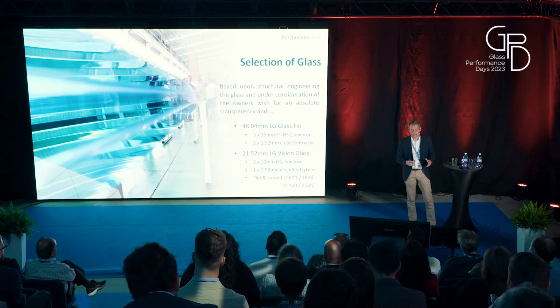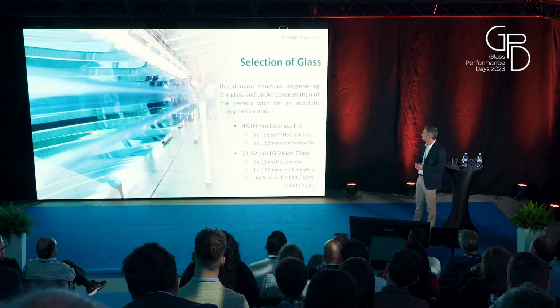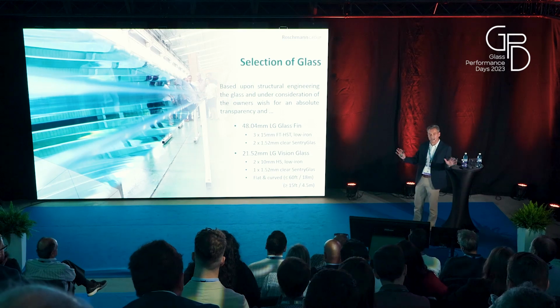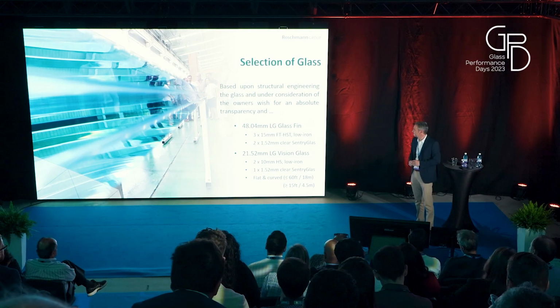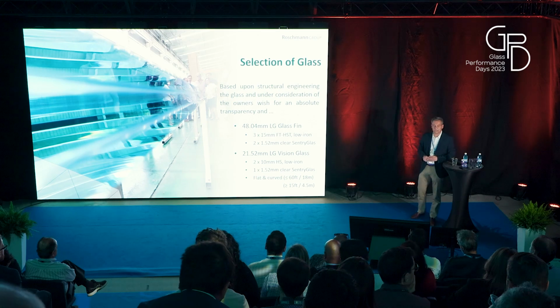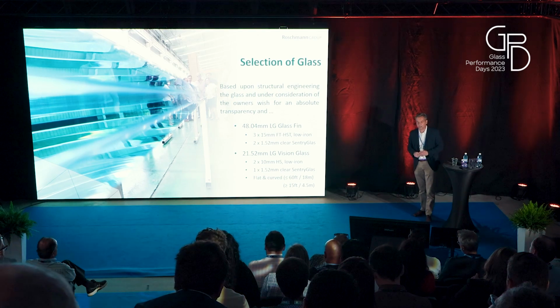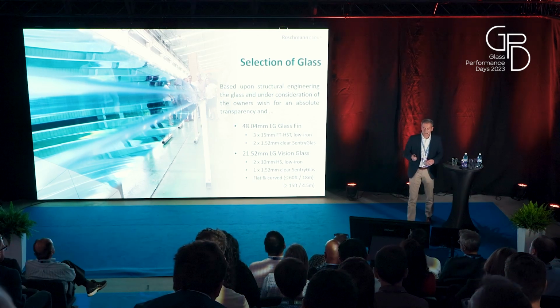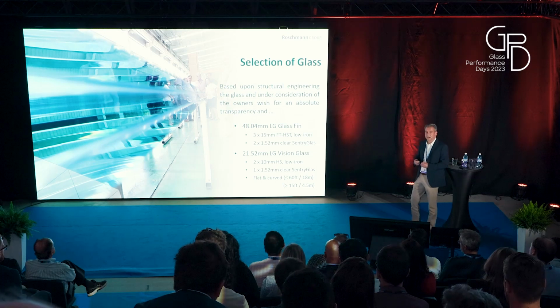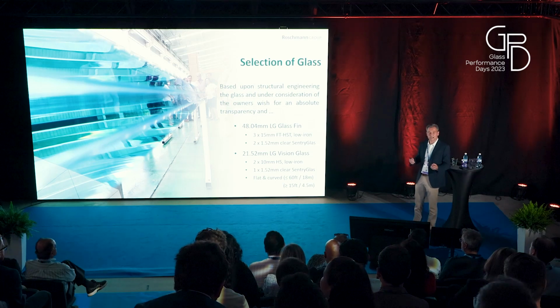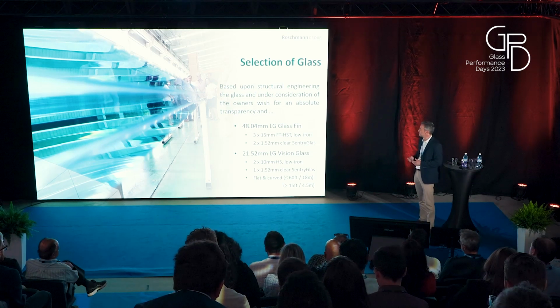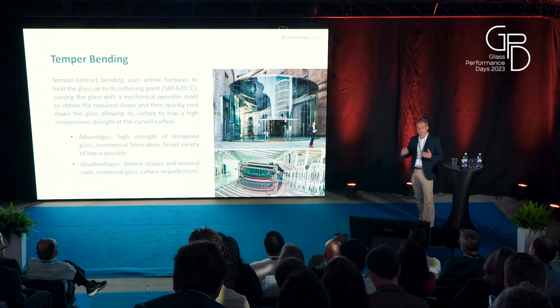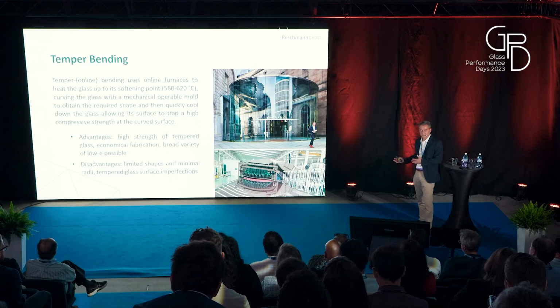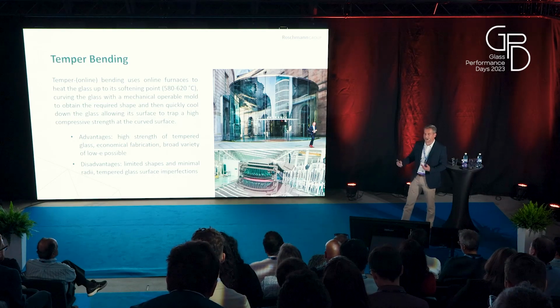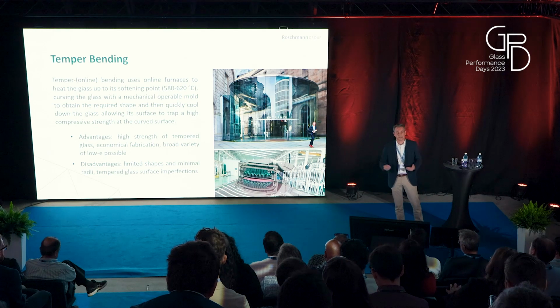We were dealing with 2 times 10 millimeter heat strengthened glass for the vision glass, and 3 times 15 millimeter fully tempered glass for the fins, which are laterally supporting the glass. So in that particular case, temper bending was the technology to choose. And when we are talking about temper bending, we always need to think about the disadvantages of temper bending, right?